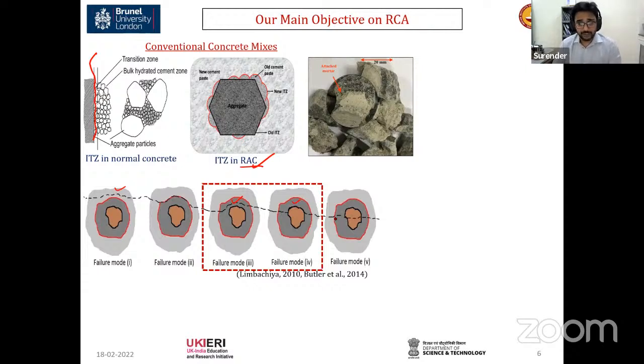And interestingly, can we make our recycled concrete aggregate concrete so strong that it is stronger than the aggregates? Can we do it? Yes, we have to look for this scenario. But right now, our current work is to shift the failure mode from mode 3 and mode 4 to either mode 2 or mode 1.